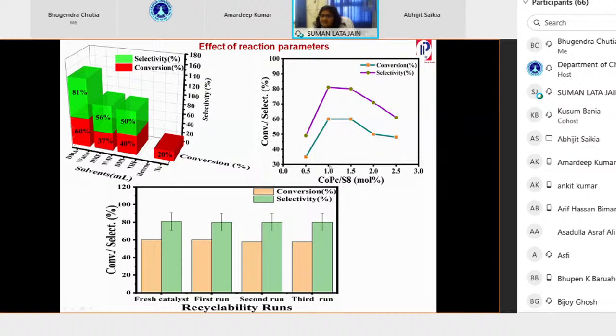Among all these, we can see that 1 mol% catalyst was enough for the maximum conversion and selectivity of the desired product. If we increase the catalyst loading, we saw that it affected the reaction adversely, mainly because it increases the concentration of the CoPc molecule on the support. Maybe it made it crowded, and so steric hindrance is caused for the binding of the substrate. So that might be a possible reason for the lesser reactivity when we use a higher catalyst dose.